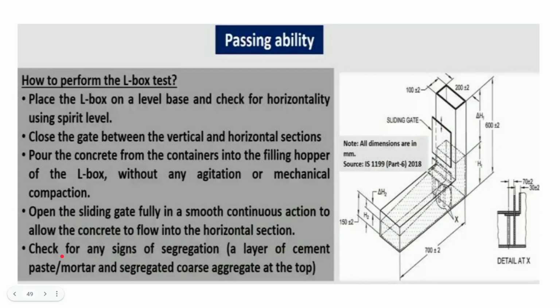Thereafter we check for any signs of segregation, such as a layer of cement paste mortar and segregated coarse aggregate at the top. From above only we check whether there is any deposition of coarse aggregate or less cement paste mortar. From the top we observe.